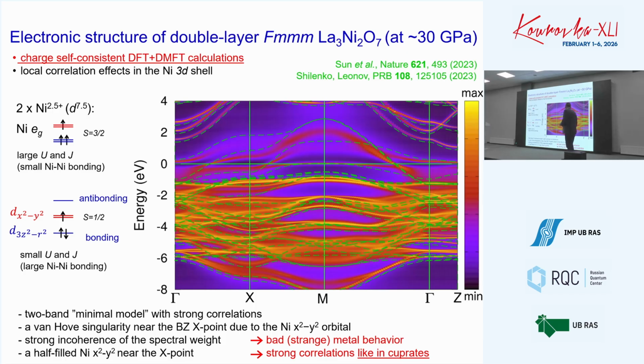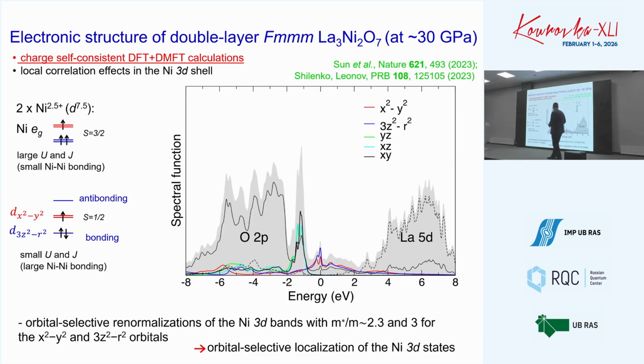We have strong incoherence of the spectral weight. This is like strange metal behavior, where strong correlations are incorporated. It is also remarkable that in the gamma-X direction we see the antibonding z square orbitals, but these two x square minus y square orbitals are split from each other, and we end up with a half-filled state, but in only part of the Brillouin zone. And this is possibly the origin of strong correlations in this state. There is, again, a smoking gun that non-local correlations will be pretty important in this material, like in cuprates. At the moment we are not able to answer this question about non-local correlations, but possibly in the future we are trying to work on this.